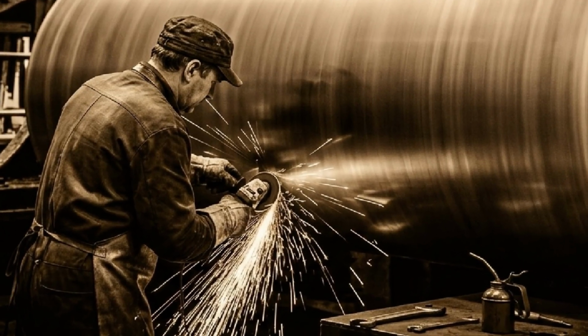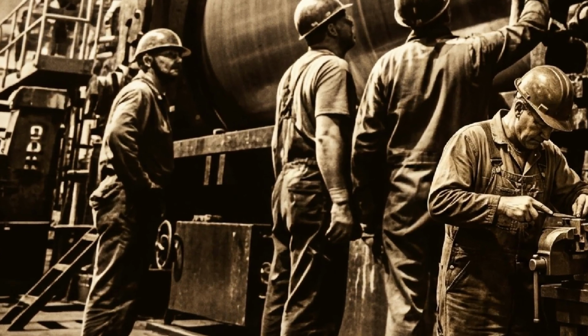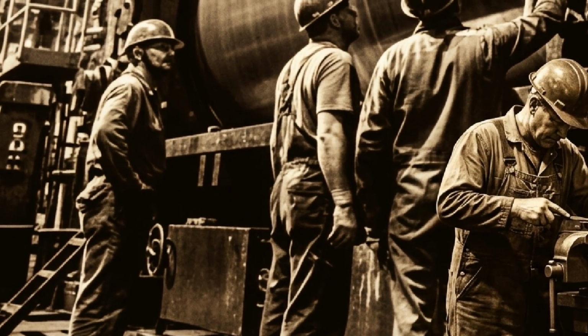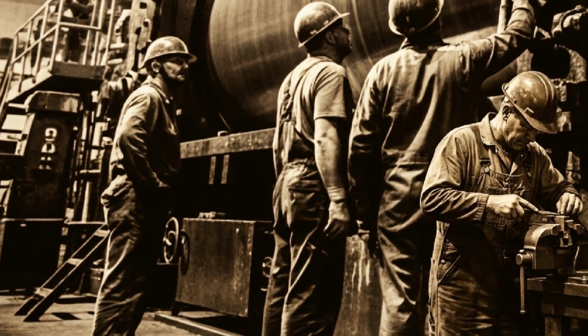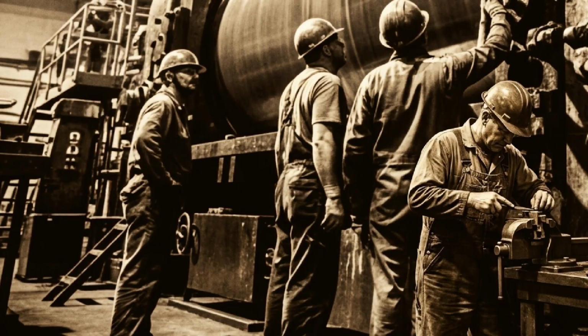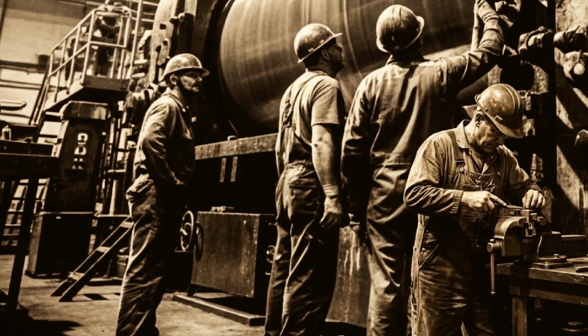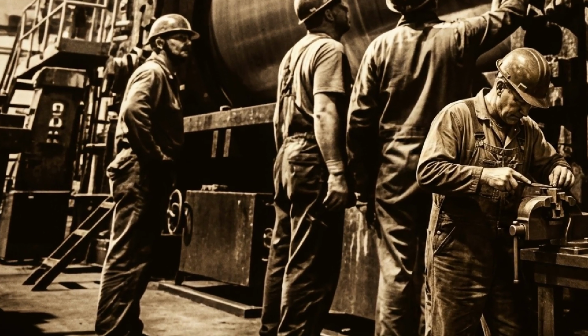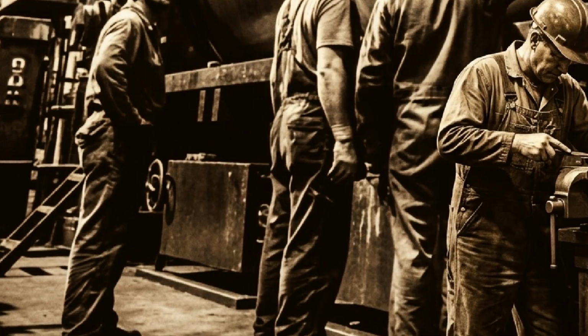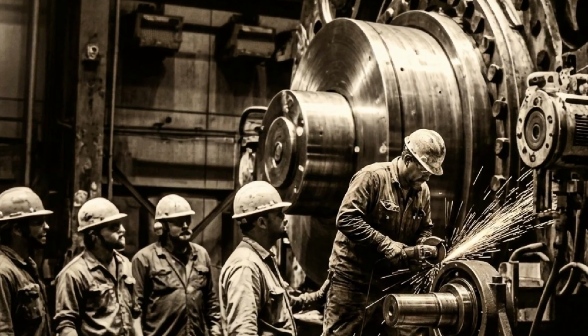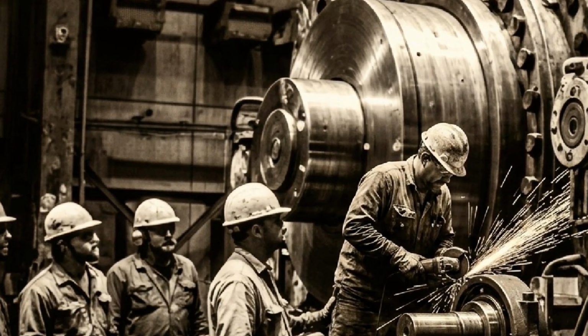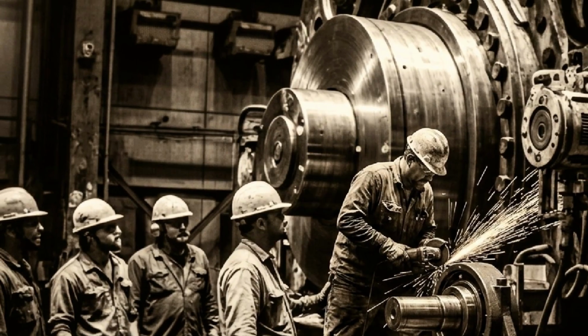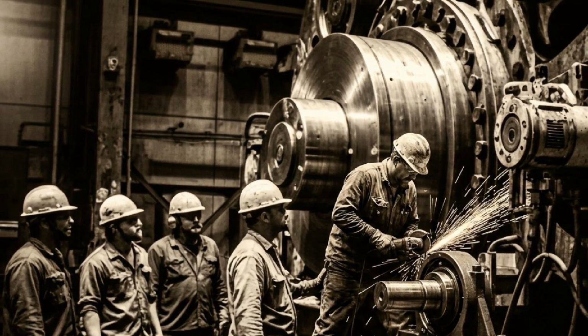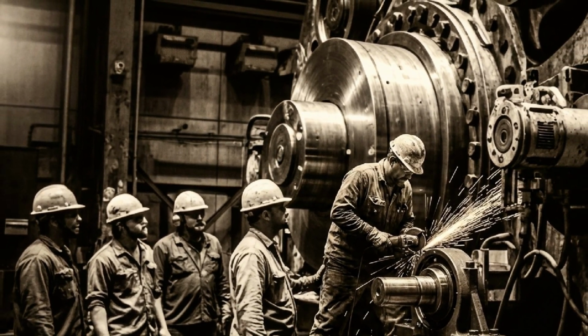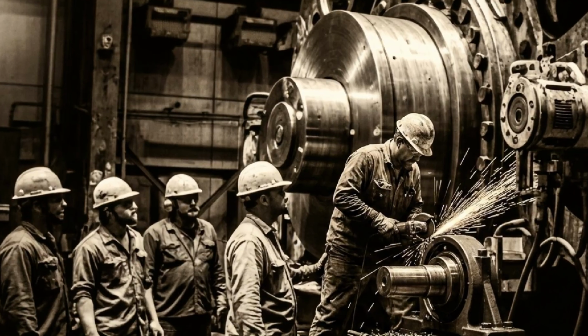When it reached a critical size, the remaining cross-section of steel could no longer support the mechanical load. At that instant, the roller fractured. This was not an explosion in the chemical sense. No fuel ignited, no pressure vessel burst. Instead, enormous stored mechanical energy suddenly lost its containment. The rotating cylinder split under internal stress while still moving.